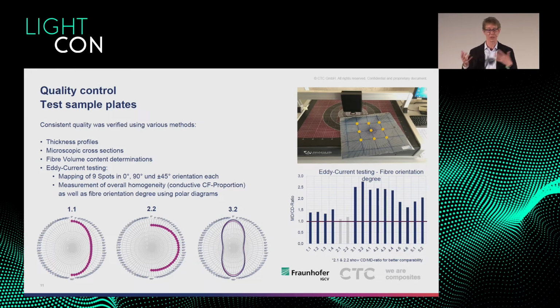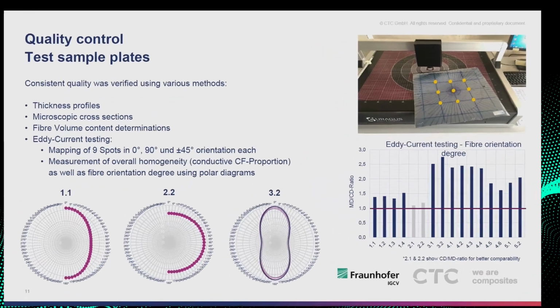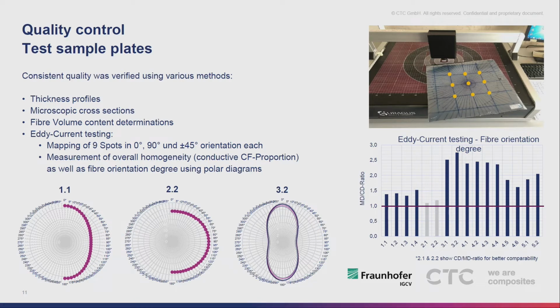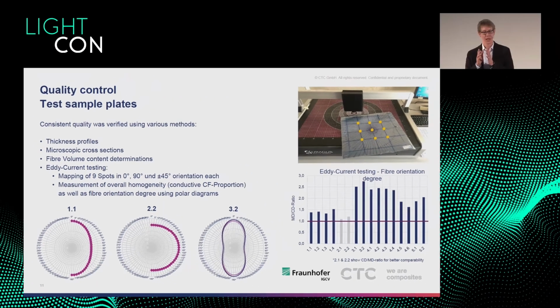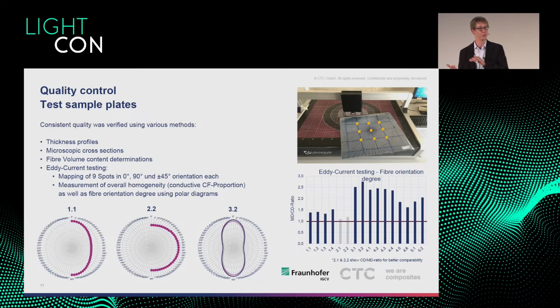These are the polar diagrams, which depict, on the left side of the slides, tensile strength over orientation of the textile. With 1.1 and 2.2, you see those are the carded textiles that are just combed nonwovens. And you see an almost circular shape of the polar diagram, which practically means you have a slight preferred orientation in UD direction, and you have a lot of fibers in other directions. 3.2 is one of those examples where we haven't worked with a carded veil, but with a sliver that had subsequently been stretched. And there you see very well what we are used to seeing with UD textiles. We see a very tight polar diagram along the 0-degree axis, and very few fibers in other directions, especially in the 90-degree direction. And that is actually what we are looking for.